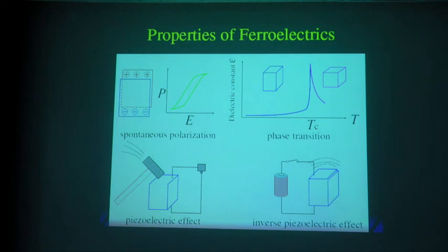No, see, soft phonons, I won't use the word assure. If they are there in the phonon discussion, they will have implications that you can calculate in thermodynamics. It has to appear in this. It depends on which material you are using. If it has soft phonons, it's very likely to be very interesting. That I can tell you for sure. In the DOS, you will see peaks at very low frequency, below 100 inverse centimeters, which is like 10 milli-electron-volts.